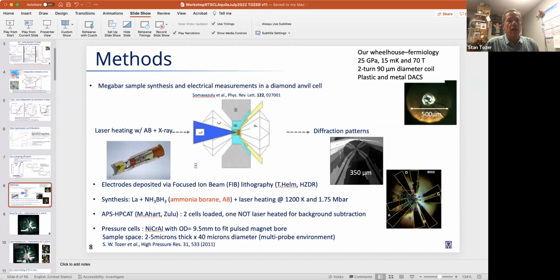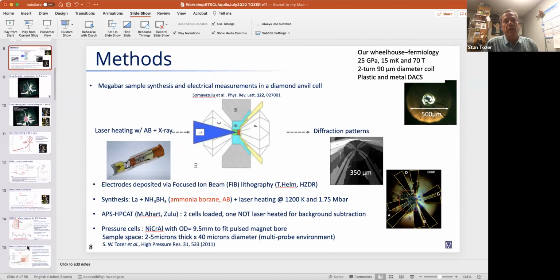All right. So our methods, just to give you a quick rundown on that, I designed a cell based on Eremets' beautiful design that he published in his book that every high pressure experimentalist has. And it worked beautifully. It's very small. It's 9.5 millimeter in diameter, 39 millimeter long. Uses this very nice Russian spring and is crazy stable. After a year and a half, the pressure of 175 was maintained throughout that year and a half that the cell was alive until it finally died from hydrogen diffusion into the anvils.